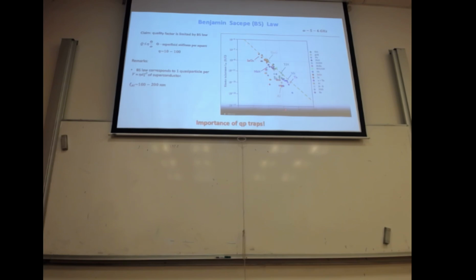He looked at different materials and different resonators built by different groups, and the resonators were always around 5-6 gigahertz. What he found is that all these measurements follow a sort of line. We call it the BS law, and Michel immediately said these laws need to be falsified. But from this law, what we estimate is that for all these materials there is always a quasi-particle density. So we know that there are always some non-equilibrium quasi-particles.